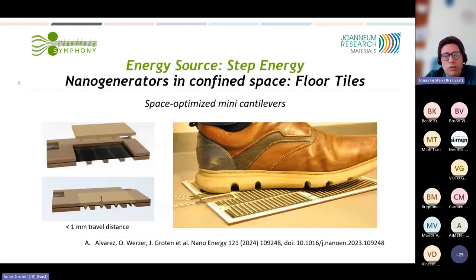In that sense, we thought about how to realize it, and it was clear that to maintain the feeling of a floor, we need a very small mechanical actuation. So we came up with a solution of mini cantilevers, which are basically small PVDF TrFE cantilevers pressed down in a small space, and we limited ourselves to below 1 millimeter of travel distance to keep the feeling of walking on a rigid floor. On the right side, there is a mock-up of the final device where these mini cantilevers are basically distributed in a floorboard. This was also recently published in Nano Energy, so you can find a lot of details on this concept there.